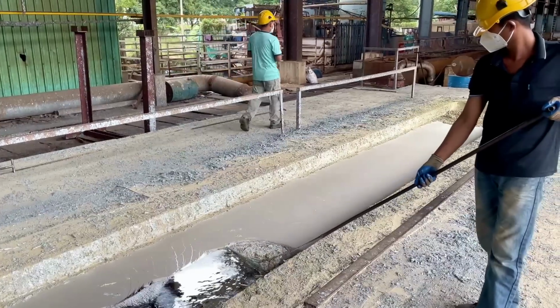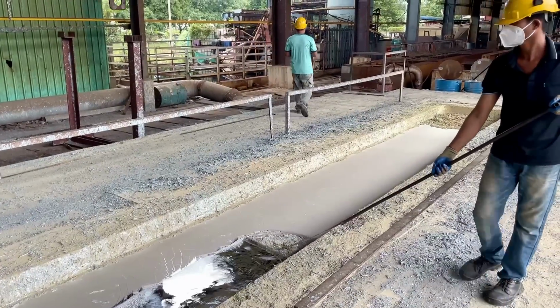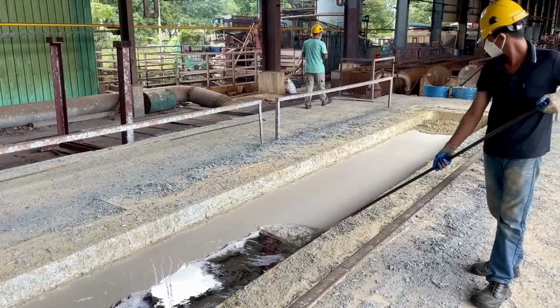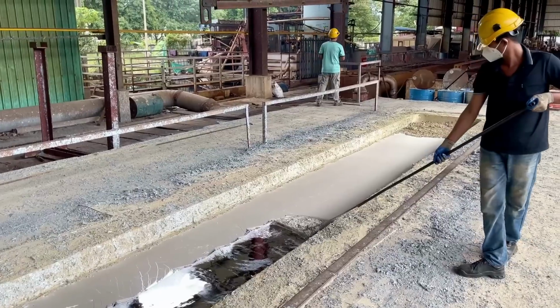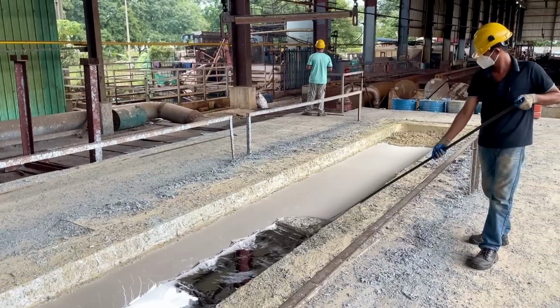The cleaned and fluxed chain is then heated to a high temperature, typically around 450 degrees Celsius or 840 degrees Fahrenheit, at which temperature the zinc becomes liquid.